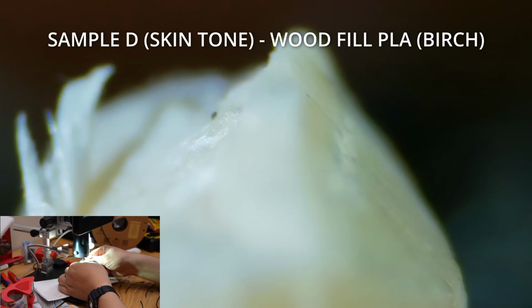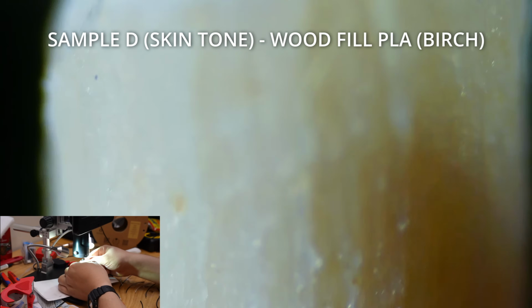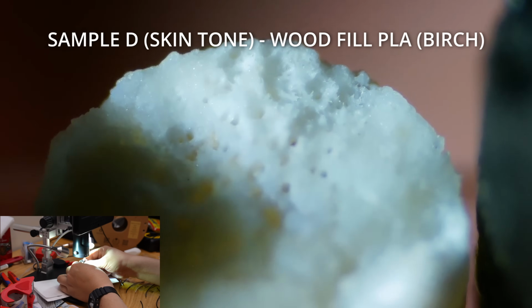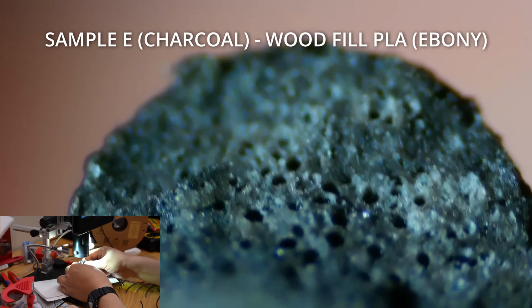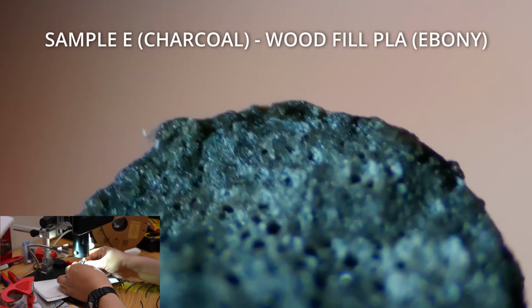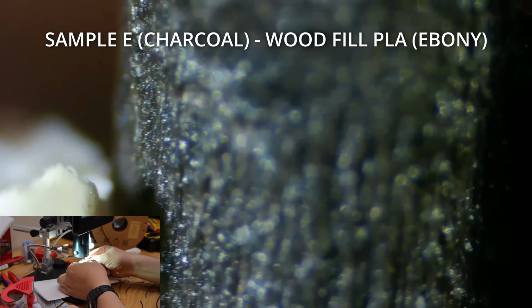Sample D. This is a wood fiber reinforced filament. So in this wood fiber filament, you can see these little bubbles. There might be some air trapped inside of the actual wood fibers. That's probably going to hurt your tensile strength and stiffness of the material. Let's move on to the one next to it. This is another black filament, and this one also has quite a few bubbles in it. I don't see any long fibers sticking out of it though, and that's because this is also a wood fiber reinforced filament. So despite the surface being pretty rough looking, similar to the carbon fiber filaments, I don't think this is going to pose much of a hazard to you.